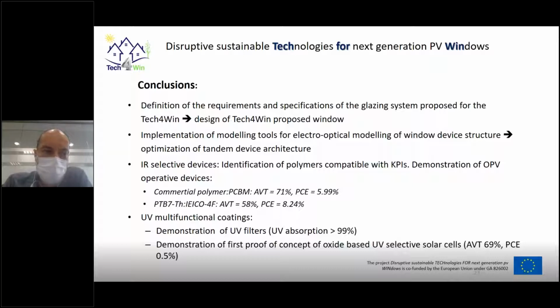As I commented, we have done very strong work in the development of infrared selective devices, with the identification of polymers compatible with the KPIs and the demonstration of operative OPV devices, where we have two potential candidates. One allows us to have very good visible transparency at the level of 71% with an efficiency at the level of 6%. In the other case, we can reduce the transparency to 58%, but still have a very promising efficiency higher than the expected value: 8%.